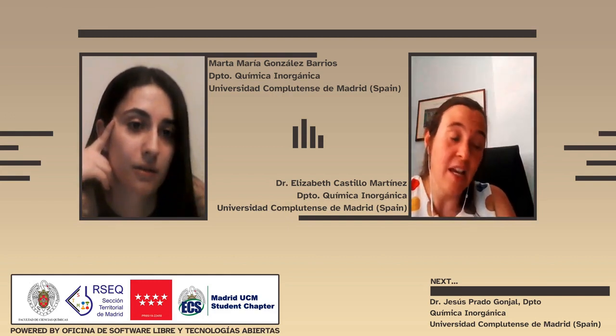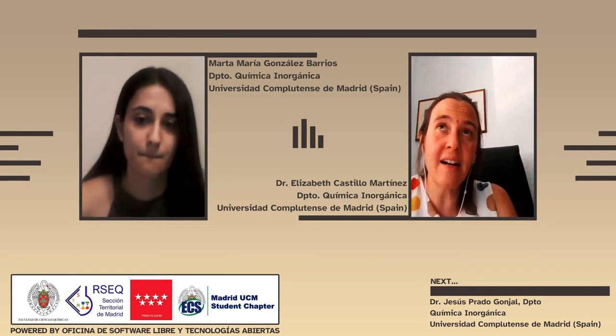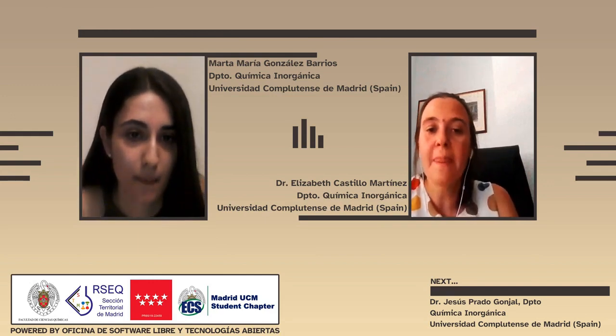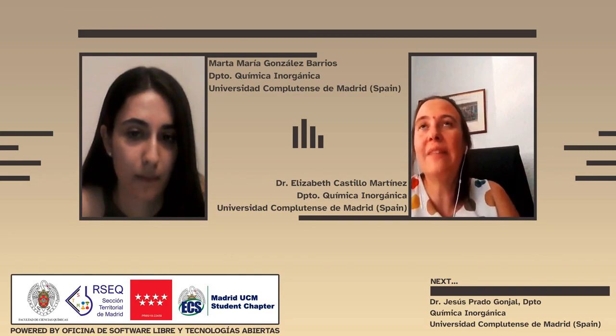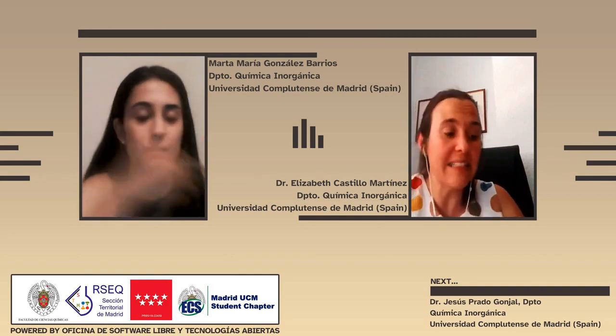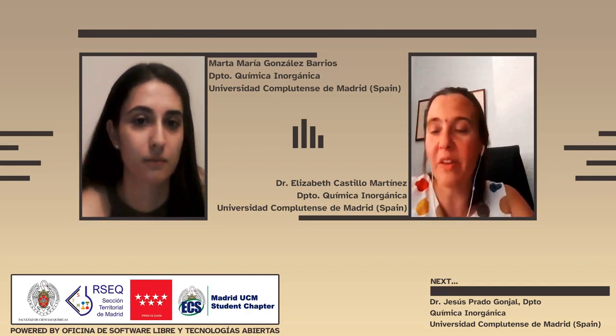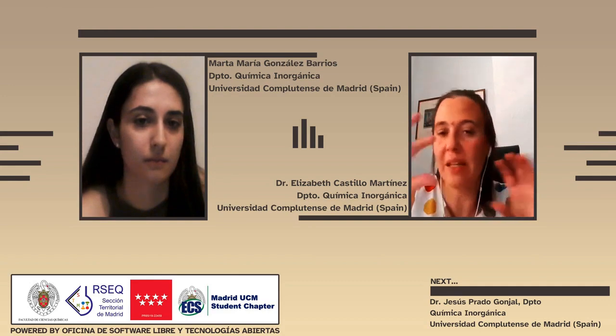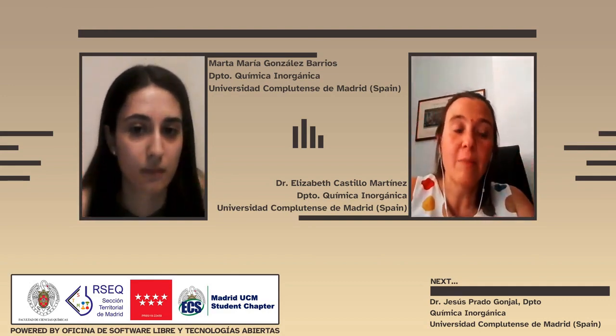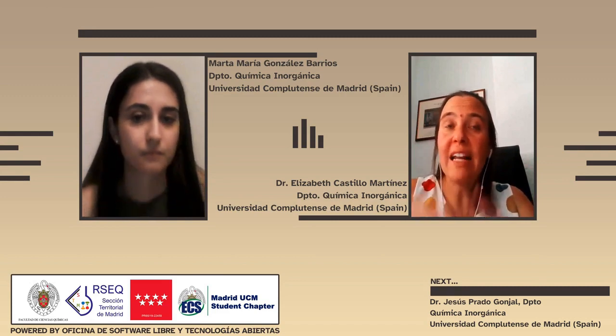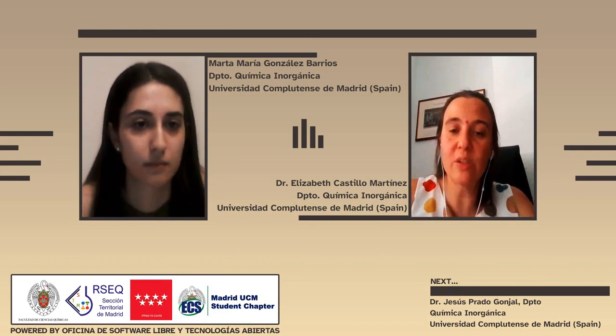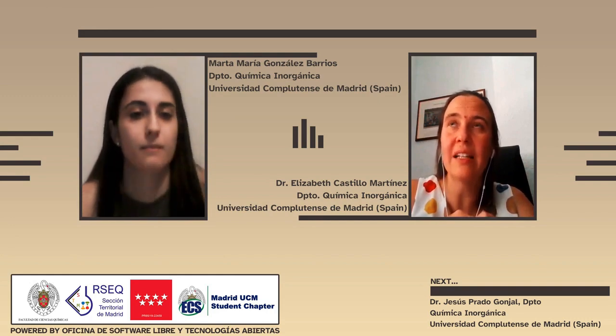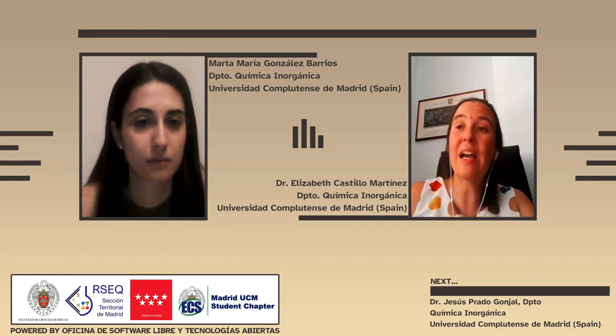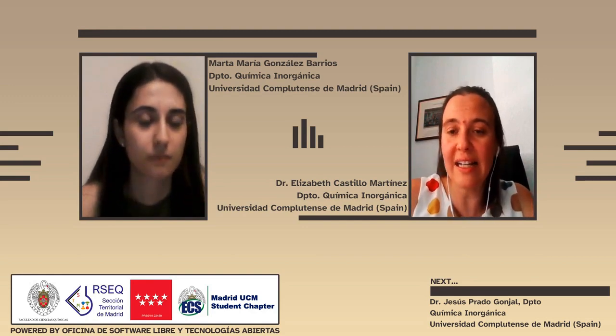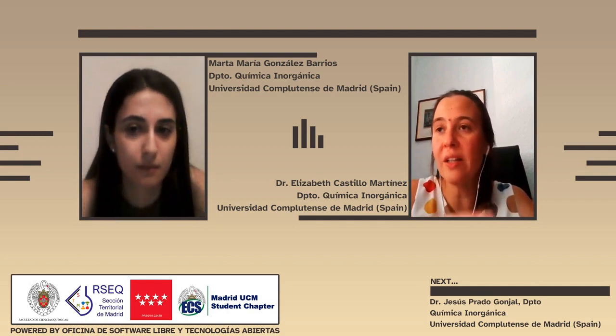This is interesting. I mean, of course, Schiff bases are prone to hydrolysis in contact with water. But at least the polymeric materials and the salts we have prepared don't show an extreme reactivity. You can keep them outside in a vial. You don't need to have them in the glove box. But I have to say, we have not actually measured very long-term cyclability, if this is what the question refers to, if it refers to their stability in the electrolyte. They seem stable, but we have not measured thousands of cycles, only focused on showing their initial electrochemical properties.